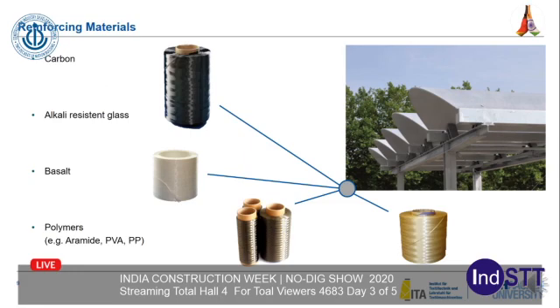The reinforcing materials are usually carbon and alkaline resistant glass, as mentioned before, but in addition basalt fibers and polymer fibers, for example aramid, PVA or PP fibers, can be used. Here, the reinforcing materials can be tailored to each application. For example, if very high strength is needed, carbon is the material of choice, but of course carbon fibers are quite expensive, so if less strength is suitable, it's better to use alkaline resistant glass or basalt fibers.